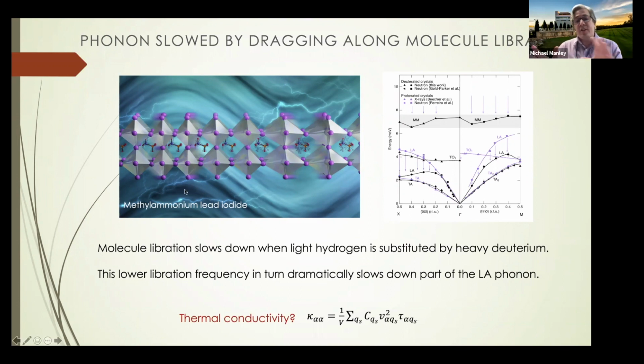So the molecular libration slows down because I've made the N groups heavy, the hydrogen heavy, by swapping it with deuterium. And then this lower vibrational frequency in turn slows down the longitudinal acoustic phonon. So that's very interesting. And it opens the question, if you go back to this equation for thermal conductivity, the thermal conductivity depends upon the velocity squared, and this is a large contributor to the thermal conductivity. We weren't really sure which way this was going to go, but we had a hunch that it would go down. And in the next part of the talk, I'll talk about how you can get tricked by these things, because you get one effect in some places and things happen in other places. But it turns out in this case, this did just what we wanted it to do.